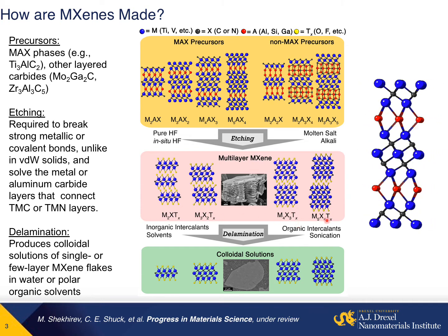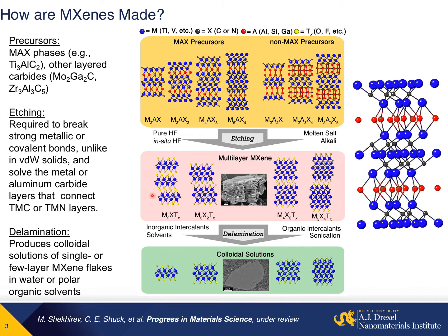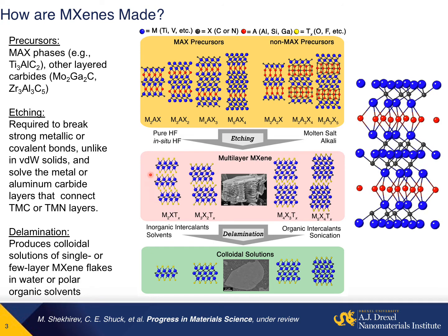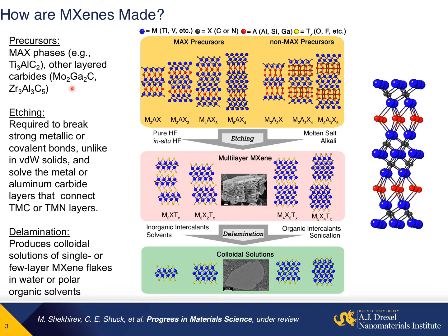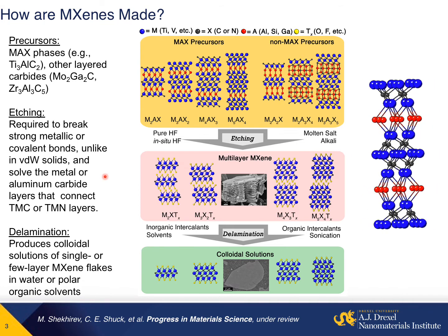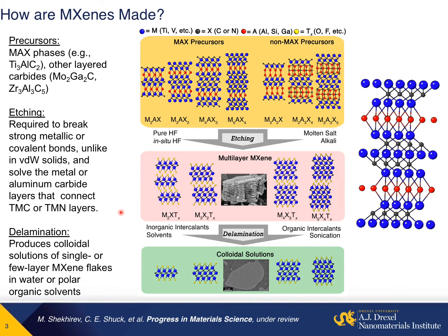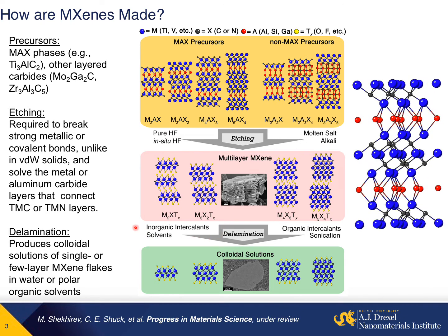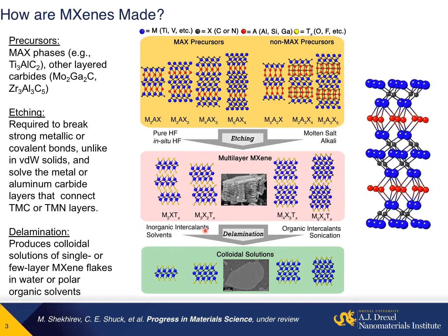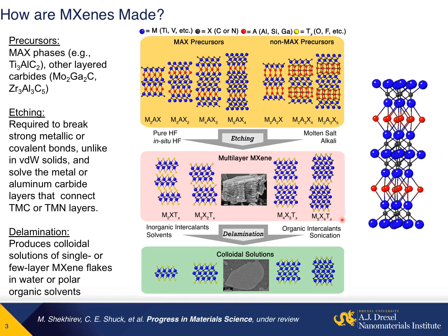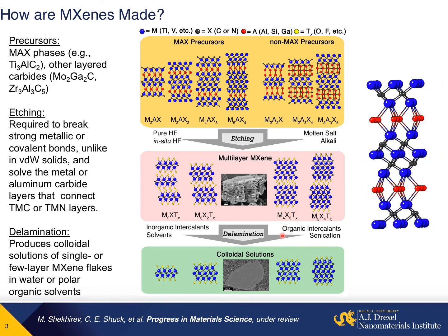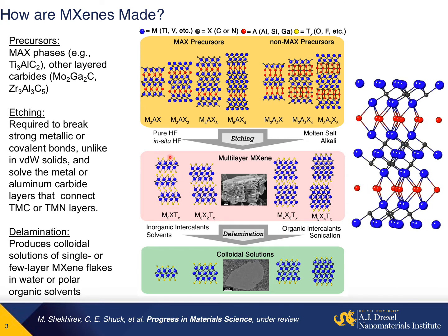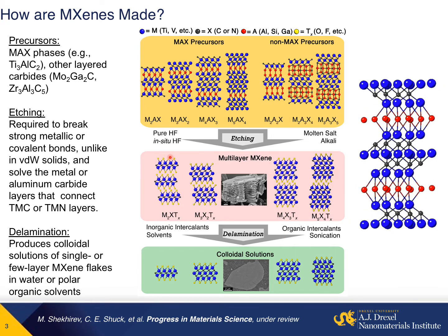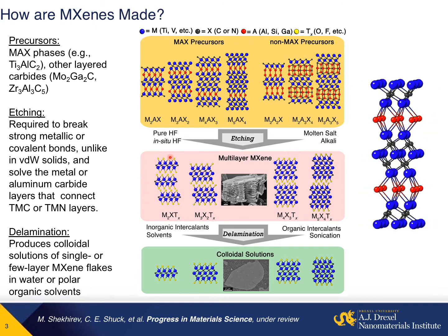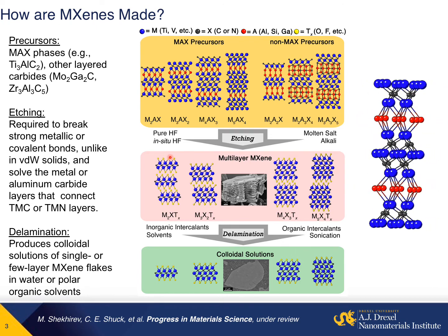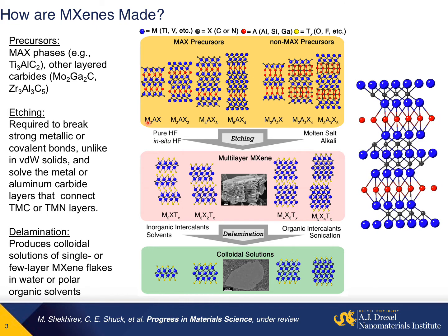After this etching process, you're left with what's called a multi-layer MXene. So all of these two-dimensional sheets are held together by van der Waals forces. And to separate these sheets, you can use a variety of delamination techniques, such as using inorganic intercalants, such as lithium, using different solvents, such as DMSO, or using organic intercalants, such as tetramethylammonium hydroxide, or just by using mechanical sonication. And what you're left with after this delamination is a stable colloidal dispersion of few layer or single layer MXene flakes in water, or a variety of other solvents of your choice.